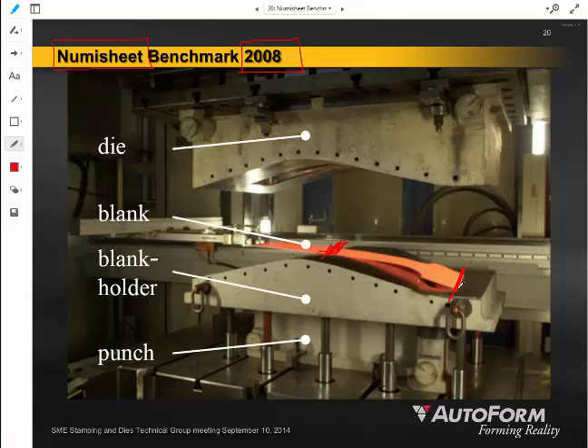And as soon as that die starts making contact with the sheet metal, the die is going to start acting like a heat sink for the material, drawing out some of that heat, causing it to cool or quench maybe a little bit earlier than was planned. And therefore, when we talk about hot stamping, hot forming, we've really seen that this is something that's going to be very reliant on our ability to engineer and mathematically simulate these forming operations in order to assure that we get the product characteristics that we finally wanted.